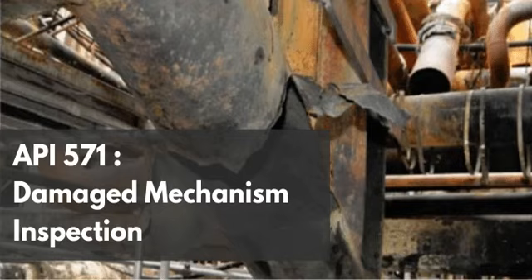Okay, phase separation. Right, so when these susceptible alloys are manufactured at the mill, they are solid solutions. At room temperature, the atoms of iron and the atoms of chromium are just mixed perfectly together in a stable crystalline lattice. Like soap dissolved in water. Exactly. But when you subject these specific alloys to long-term exposure at elevated temperatures, you provide just enough thermal energy to allow the atoms to start moving. They get mobile.